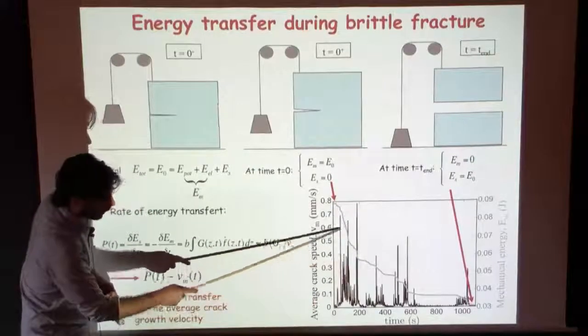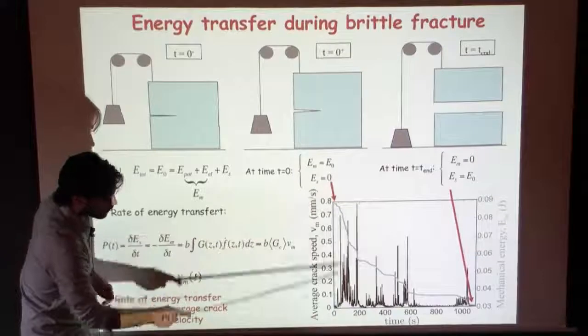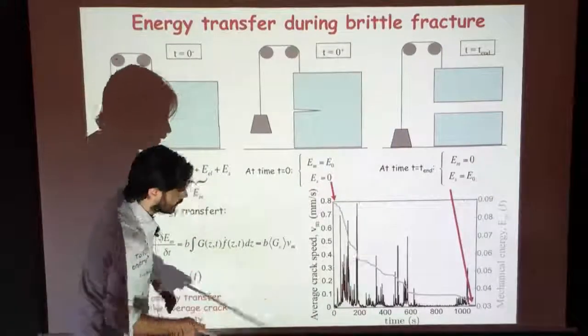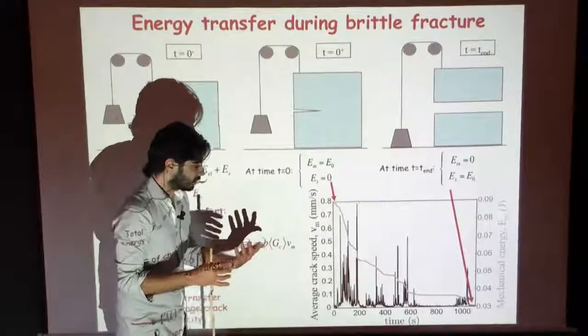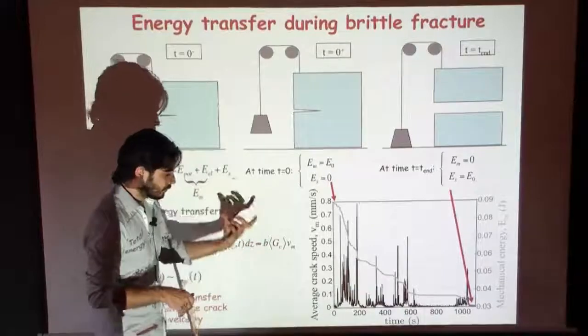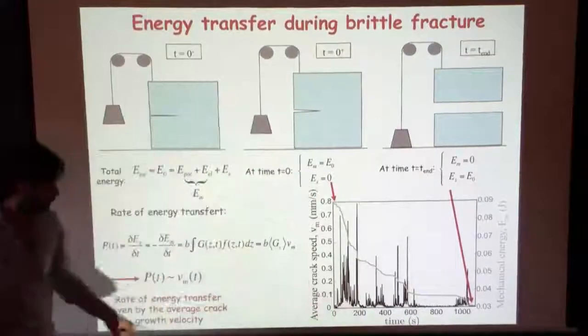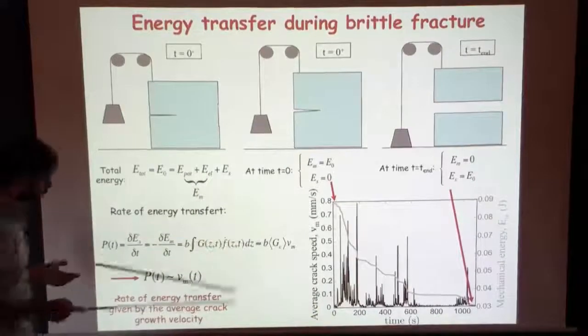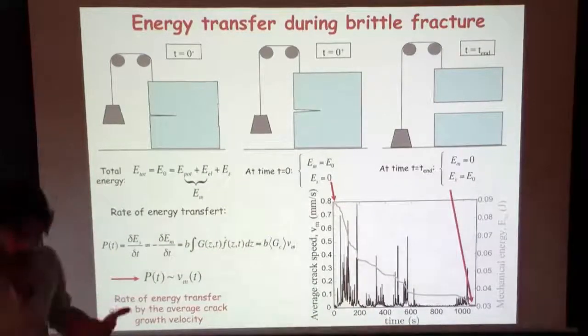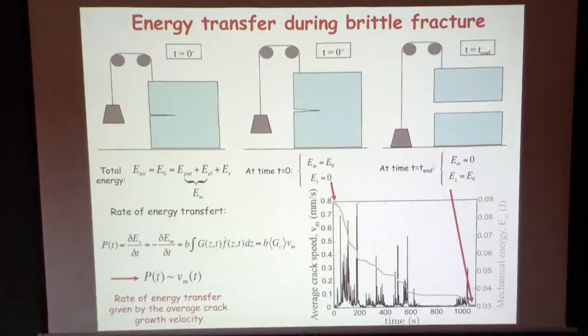You clearly see that when you have a drop in the mechanical energy, you have large velocity. So if you want to have the energy transferred from mechanical to surface over some time, you just integrate the velocity signal, okay? And you have a constant prefactor, sure, but okay, that's the idea. That's why we want to focus on the average velocity of the crack. That gives a lot of information about the avalanche defined from an energy perspective.